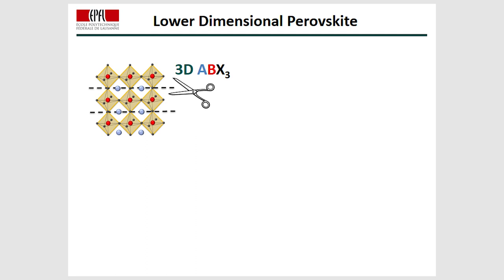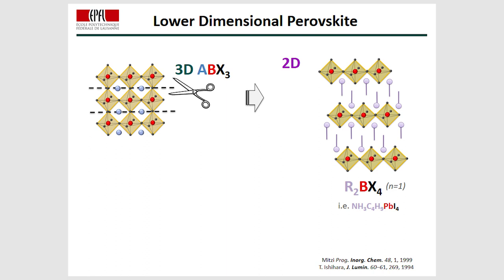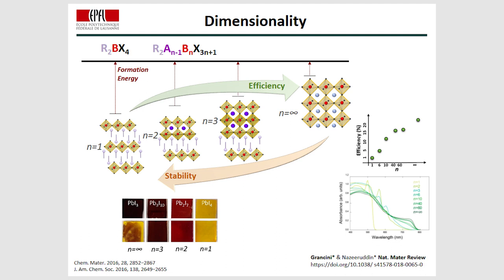A new family of stable perovskites can be obtained by slicing the 3D perovskite network along the inorganic plane. A pure 2D perovskite is obtained when using large organic barriers — in this case we have only one layer of the inorganic network, so n equals 1. However, it is also possible to form quasi-2D perovskites depending on the number of inorganic layers, so n equal to 2, 3, and so on. We can thus modulate the dimensionality going from 2D (n=1) through quasi-2D to full 3D perovskite.